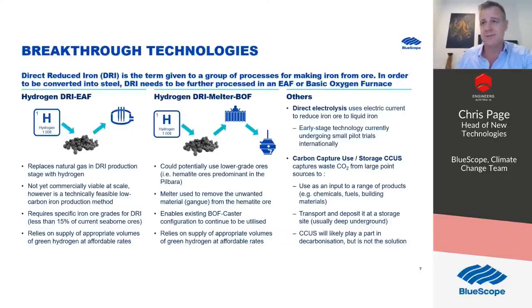Now, the reason that's significant is you actually still need energy to make a molten product. And so the reason you can't use hydrogen as opposed to coke in a blast furnace is that the blast furnace process is a liquid iron process. If we put too much hydrogen in, that liquid will turn to solid and you'll have a blocked furnace. So it just won't work. In the DRI process, however, you put in a pellet product, which is porous, and the gas can pass through that, and you end up with a solid iron product.